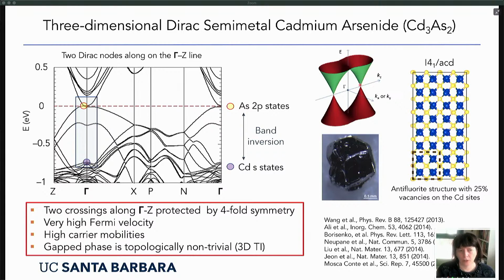Okay, so that has only two of them, so that makes things relatively simple, and they're right at the Fermi level. There's another interesting property, and I'll come back to this: the crossing is actually by mostly arsenic 2p states, and very way down, but at the gamma point, we have these cadmium S states, and so the band inversion is between these 2p states and cadmium S states, and it's very, very large. So later, when we open a band gap, for example, by breaking this fourfold rotational symmetry, we still have this very large band inversion.